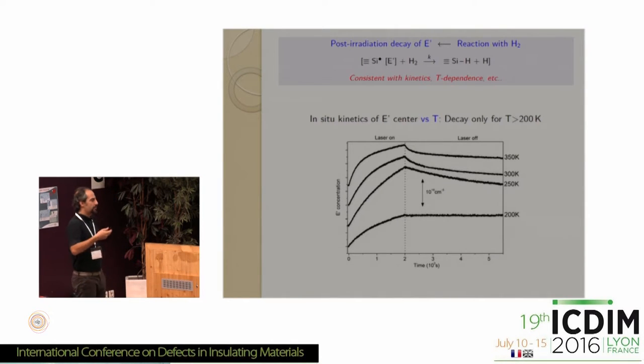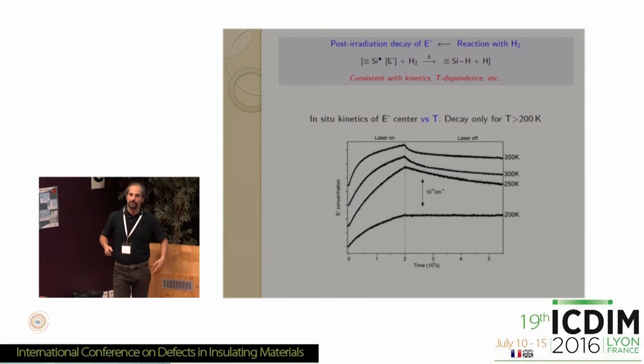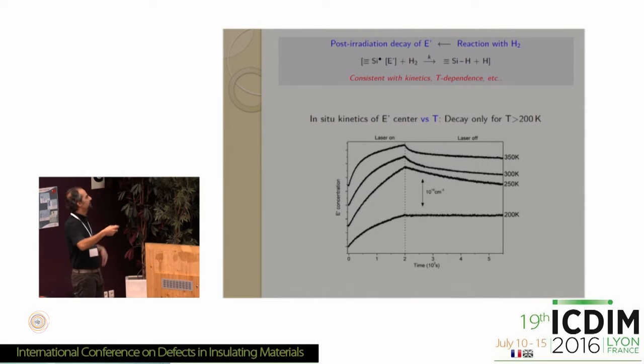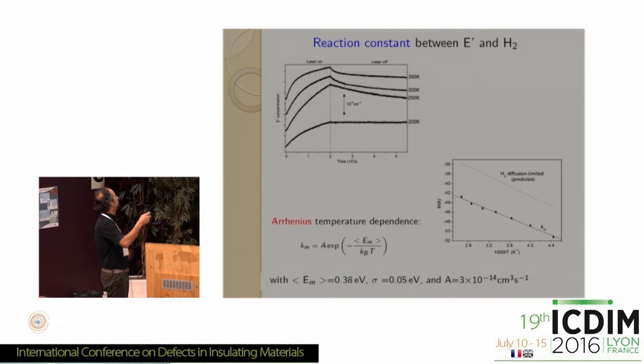One of them is the temperature dependence. There is no post-irradiation decay if the experiment is done below about 200 Kelvin. This decay is only observed at higher temperatures, higher than 200 Kelvin, and 200 Kelvin is known as the activation temperature of hydrogen diffusion in SiO2. So this is a way of seeing that this must be due to a diffusion-controlled reaction. And by this, we were also able to extract from this kinetics the reaction constant between the silicon dangling bond and hydrogen, because this is contained, of course, in this kinetics.